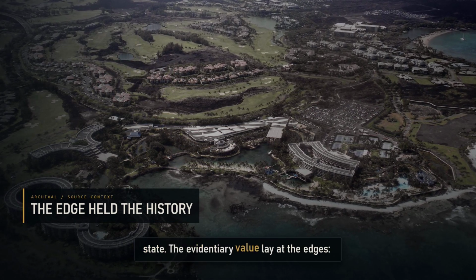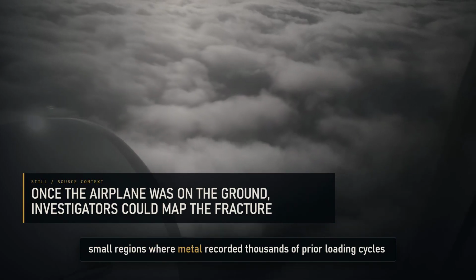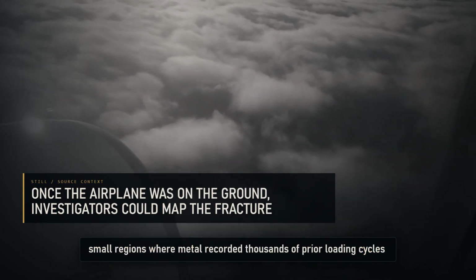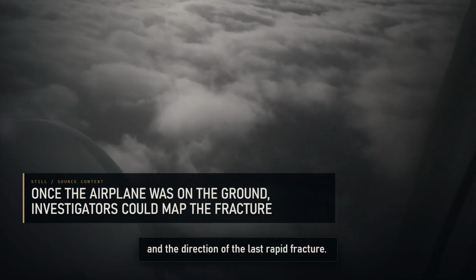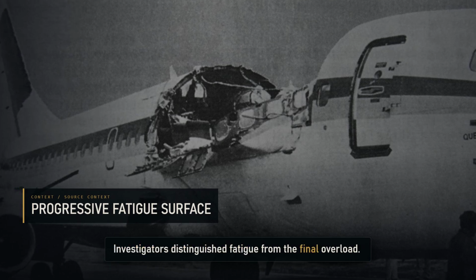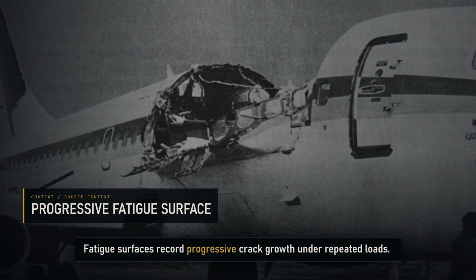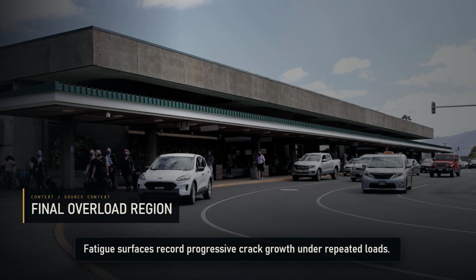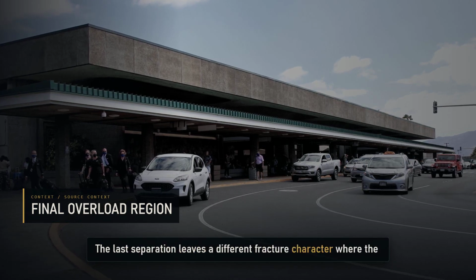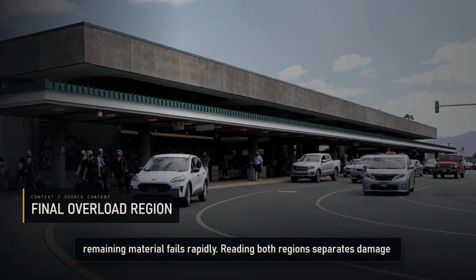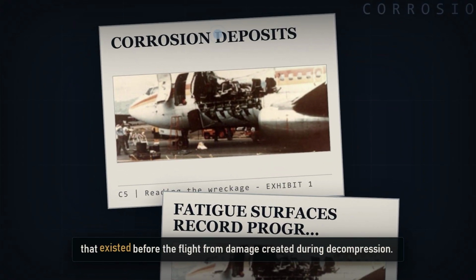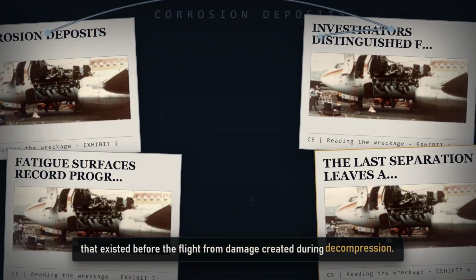The evidentiary value lay at the edges, small regions where metal recorded thousands of prior loading cycles and the direction of the last rapid fracture. Investigators distinguished fatigue from the final overload. Fatigue surfaces record progressive crack growth under repeated loads. The last separation leaves a different fracture character where the remaining material fails rapidly. Reading both regions separates damage that existed before the flight from damage created during decompression.